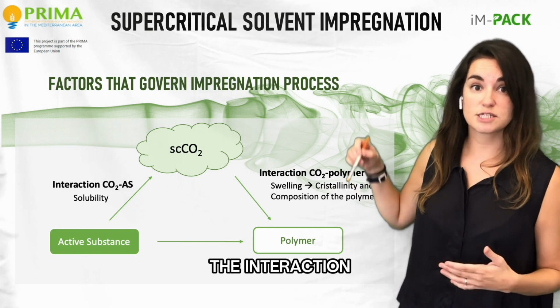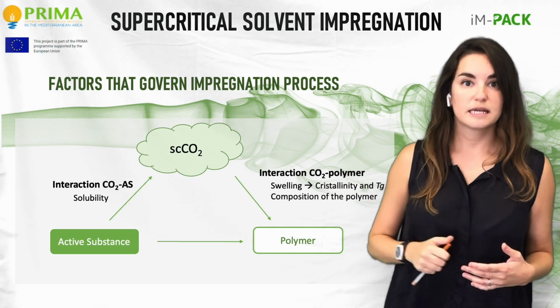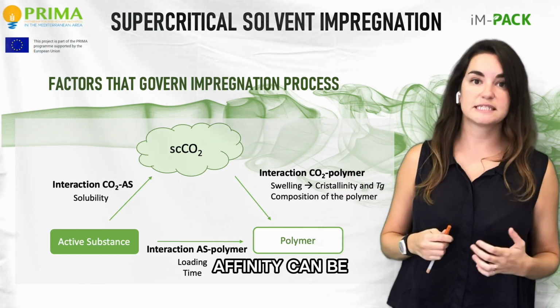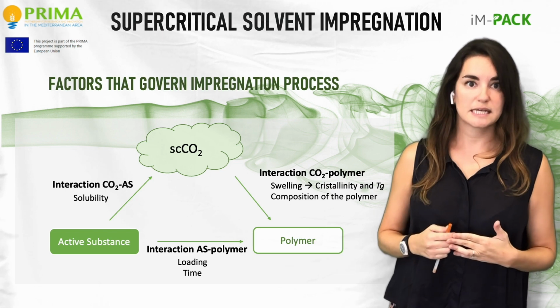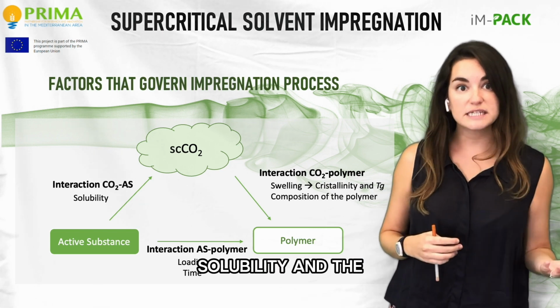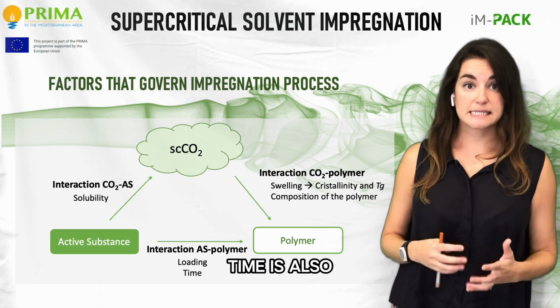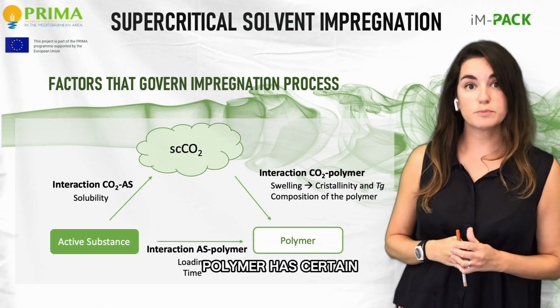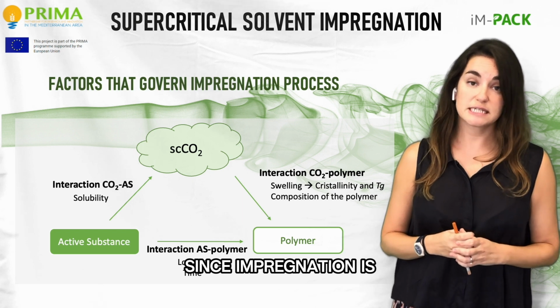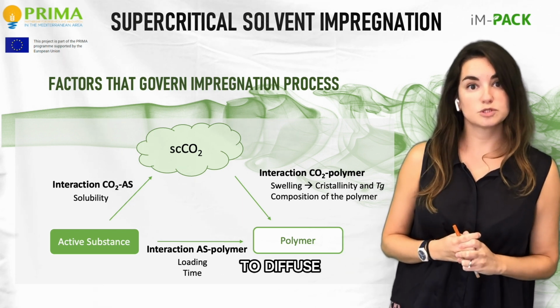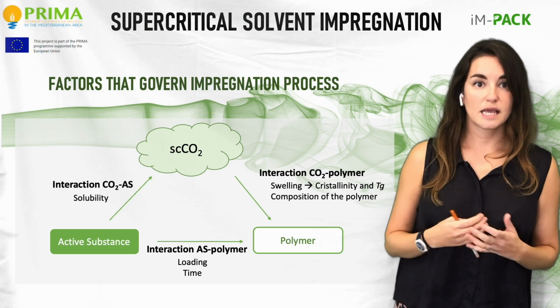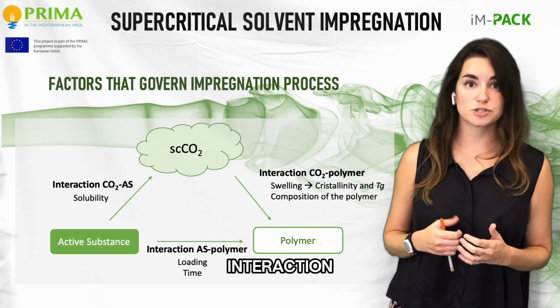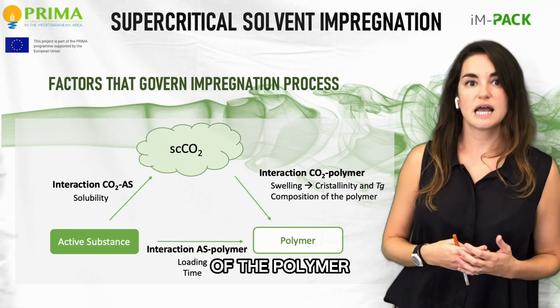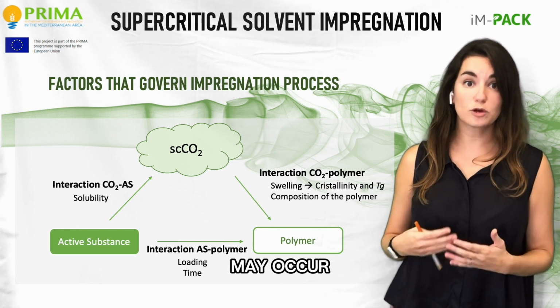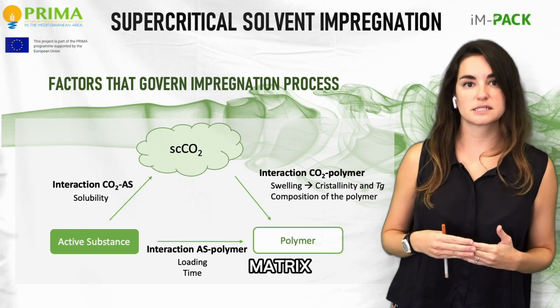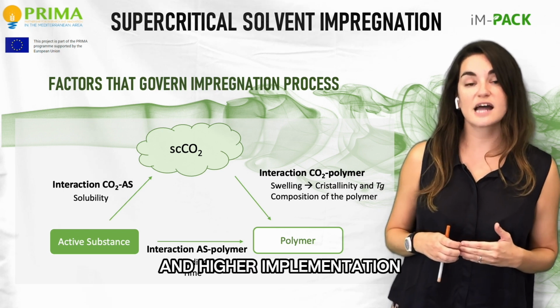Finally, regarding the interaction between the active substance and the polymer, as I mentioned before, this affinity can be enhanced by the addition of solvents, since its presence intervenes in both the solubility and the swelling capacity. Time is also a very important parameter, mainly when the polymer has a certain diameter, since impregnation is a diffusional mechanism and it requires a certain time to diffuse into the polymer. When active substance and polymer have a good interaction, the partition coefficient is in favor of the polymer, and chemical and/or physical interaction may occur between the active substance and the matrix, which could lead to a better dispersion of the solute and higher impregnation rates.